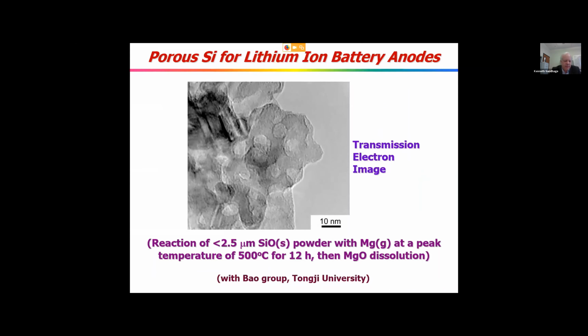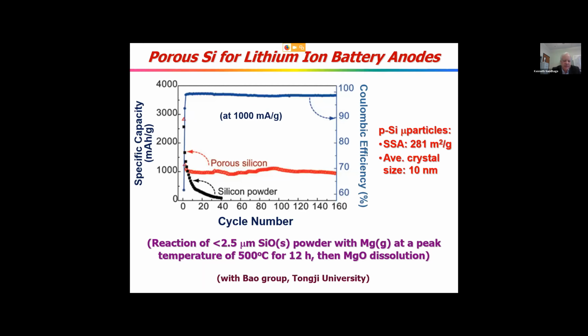We've also been doing this with Zihao Bao's group at Tongji University in Shanghai. This is the SiO powder that was made basically into Swiss cheese silicon, as you can see here in the transmission electron microscope image, and he found that the capacity of the anode was well preserved because of the porosity and nanoscale nature of the silicon over a number of cycles this way.